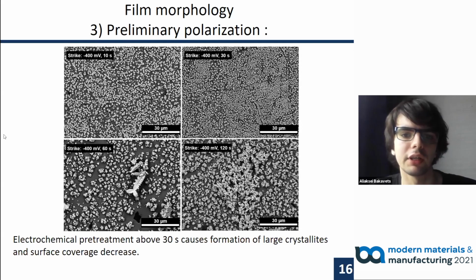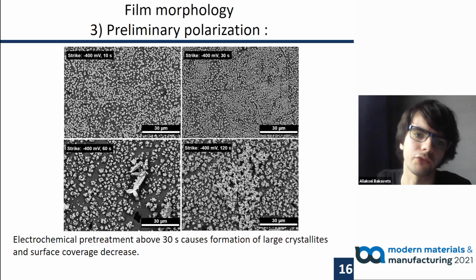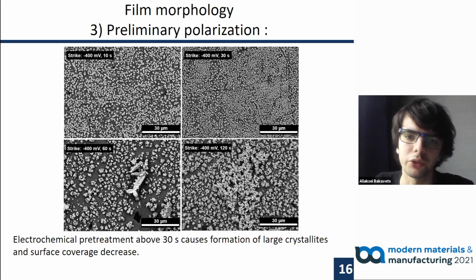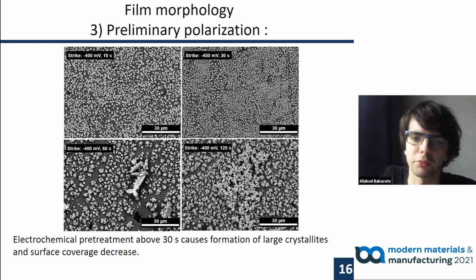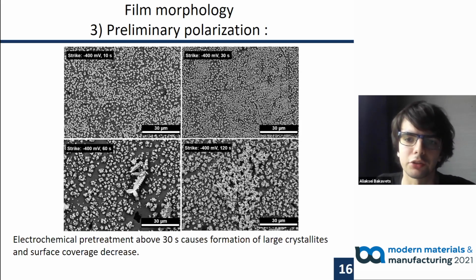In order to facilitate nucleation on bare substrate, the electrode has to be prepolarized at a potential more negative than that used for the film deposition. We used pretreatment at -400 millivolts for 30 seconds to provide uniform coverage of the stainless steel substrate surface by the electrodeposit. The excessive pretreatment led to formation of large crystallites.